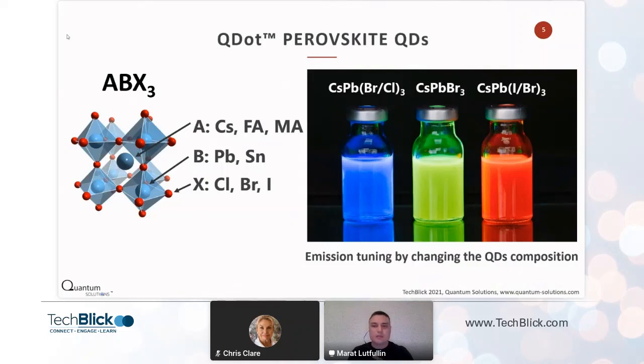The interesting thing with perovskite quantum dots is that their band gap can be tuned by changing the composition. For example, in the center is a green vial, it's cesium lead bromide (CsPbBr3) quantum dots. It's emitting green light. If we add chloride there, we can increase the band gap and the emission will be tuned to the blue range. But if we add iodide, the band gap will decrease and we will tune the emission to red light. This is a very unique and interesting thing with perovskite quantum dots. So you can get quantum dots with any color.